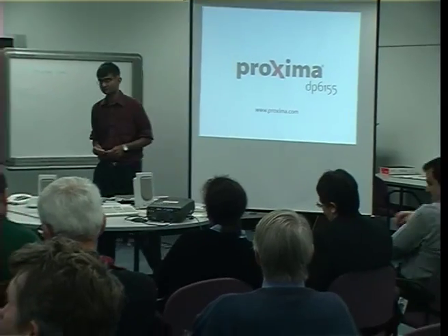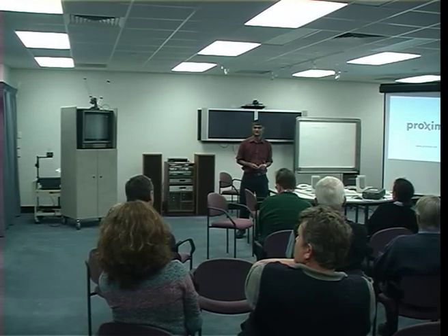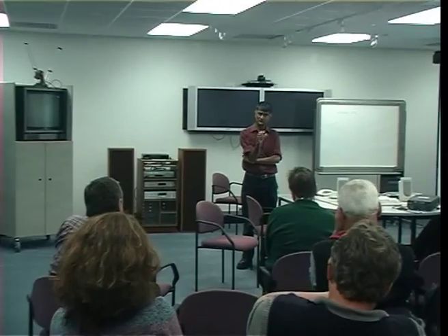So the acicular ferrite that you see consists of these small 10 micron long platelets. Now, if you have a lot of nucleation sites, then they are basically individual platelets because they hit each other before something can happen. So you mean the volume fraction of inclusions influences the size? Yes. Unfortunately, inclusion is also a nucleus for fracture, so you have to balance that.